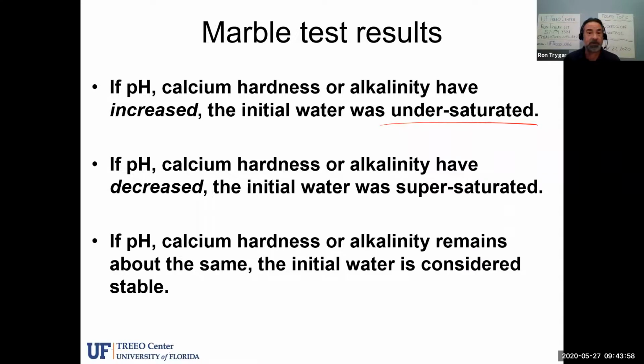If the pH, calcium hardness, and alkalinity essentially remain about the same, now the numbers might vary slightly from each other, let's say a hardness of 200 versus a hardness of 201, or a hardness of 199 at the end, well, then we would say that's essentially the same. It's within a small percentage of each other. We would say that water is at saturation, it's stable, it's not really going to make much of a scale, but it's also not going to be corrosive either. So that's kind of what we're looking for. We're hoping for water to be slightly scale forming to be protective of the water mains.